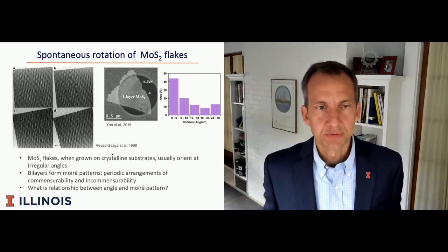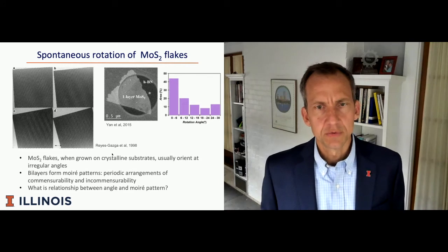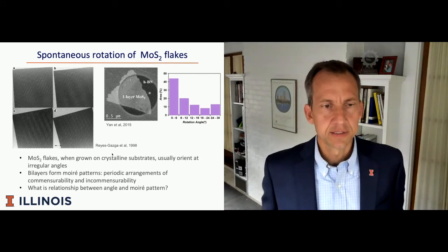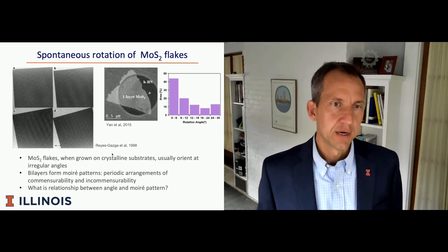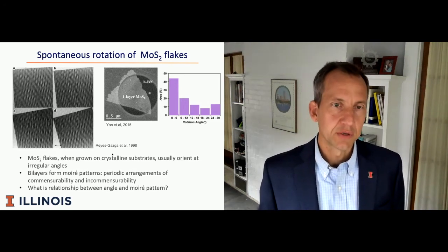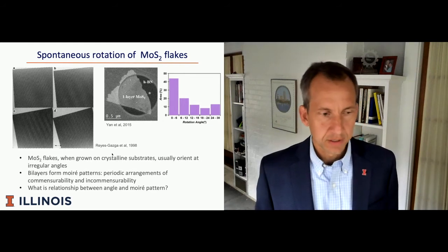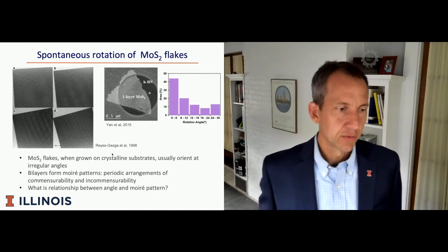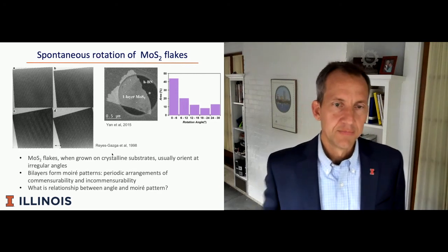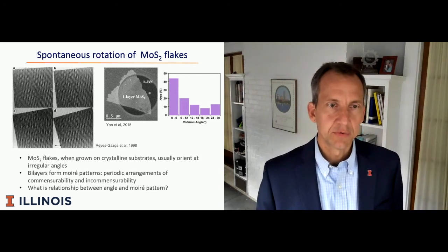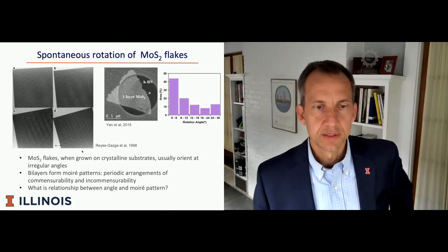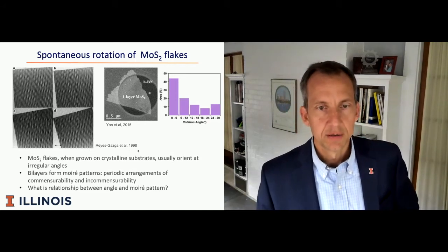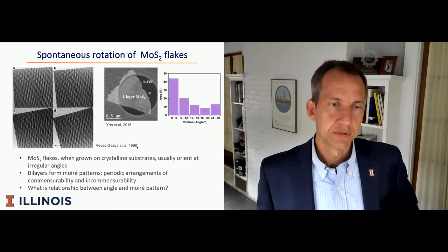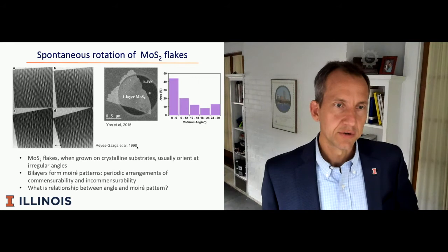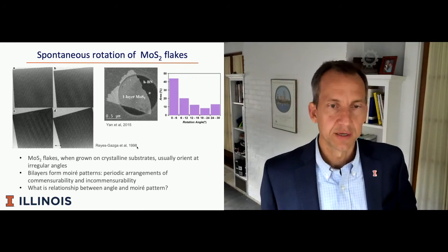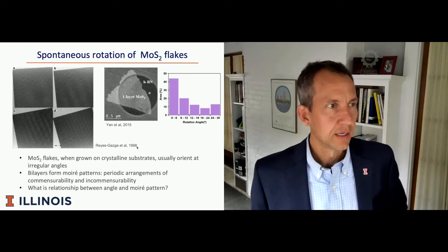This has been seen for quite a long time, and at first glance, it's perhaps surprising that the stacking would do this rather than stacking according to one of the AA or other regular stacking configurations that I showed on the first slide. The two images here are interesting to me because the image on the left was observed in high-res TEM all the way back in 1998. And so in terms of 2D material research, this is prehistoric, literally prehistoric in terms of what we know about graphene.